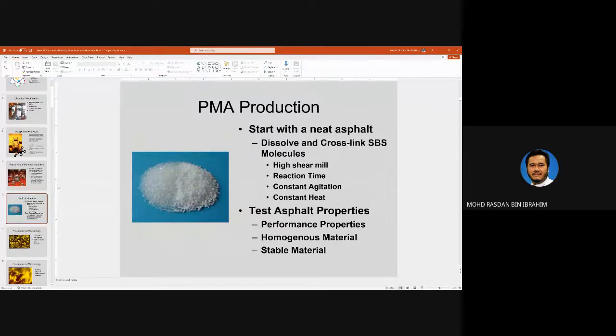So how do we mix these modifiers, polymers, with bitumen? We start with neat bitumen, meaning bitumen that has not been modified, either 80 over 100 or 60 over 70. We heat it up, usually to a temperature of 150 to 160, then we dissolve and cross-link the SBS molecules. So you pour in the SBS. You can mix it either using a high shear mixer or a normal propeller mixer. Among the factors that will affect the performance of your mix are the type of mixing, the reaction time, meaning how long you mix the polymer with bitumen, constant agitation and constant heat.